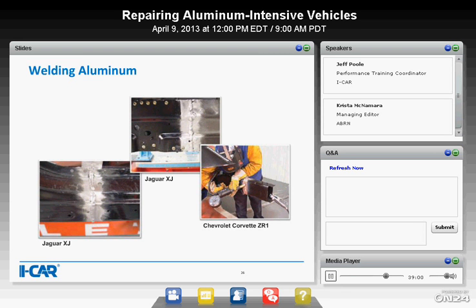Correct surface preparation and consistent joint fit up. These are mission critical. The oxidation's got to go. We cannot have any oxidation, front or back, within a reasonable distance of that weld. No coatings, no weld-through primers. We want this to be a surgically clean environment during preparation and execution.